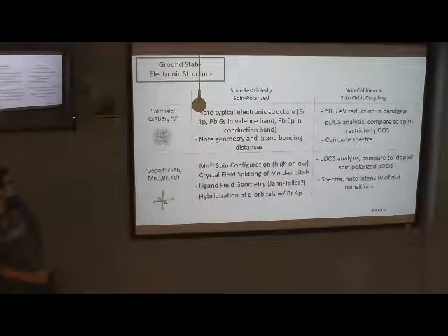So I just put up bullet points of what I planned to mention in my paper. I didn't put any figures because it would take a long time to go through them all. And I have it laid out as a 2x2 because for 2 quantum dots, we do 2 different sets of calculations for each one. So for doing geometry optimization, we do spin-restricted calculations for the intrinsic quantum dot, and we do spin-polarized for the doped quantum dot because we're dealing with transition metals, which can have a variety of different spin configurations. So you have to do spin-polarized to get the correct electron configuration.